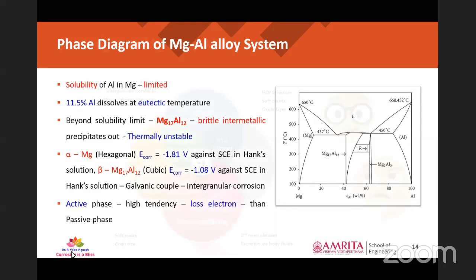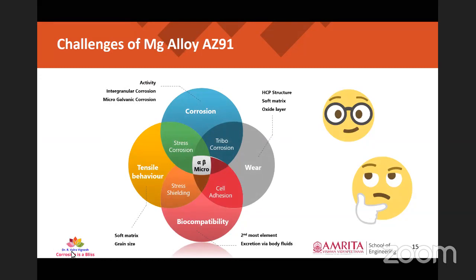Here is the list of challenges posed by magnesium alloy AZ91 for fabrication. First is its activity. Since it is a magnesium based alloy, it is highly active and will result in intergranular corrosion and microgalvanic corrosion. Coming to its soft matrix and HCP structure, it is prone to high wear rates. Added to that, the HCP structure restricts deformation of the alloy. Coming to tensile behavior, it has a soft matrix, and the grain size will determine the tensile strength of the alloy. So if we want to improve the tensile characteristics, we have to opt for grain refinement techniques. Coming to biocompatibility, that is a plus point for us because magnesium is the second most abundant element in the human body, and if in excess, it is excreted through body fluids.